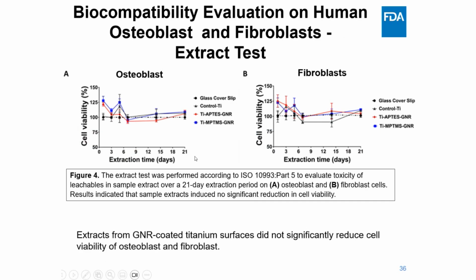So here are the data for the extract test. Over a 21 day period, extracts from both coating methods, both the GNR functionalized titanium surfaces, did not reduce viability of the osteoblast or fibroblast cells. So this indicates there's minimal cytotoxic leachables compared to the controls, and it sustained the biocompatibility.